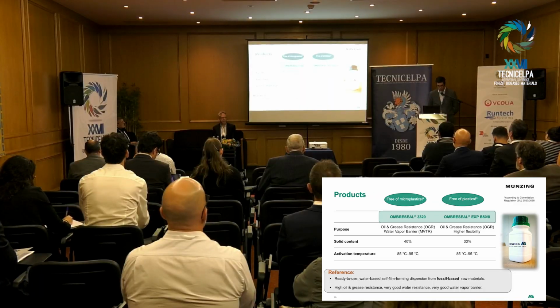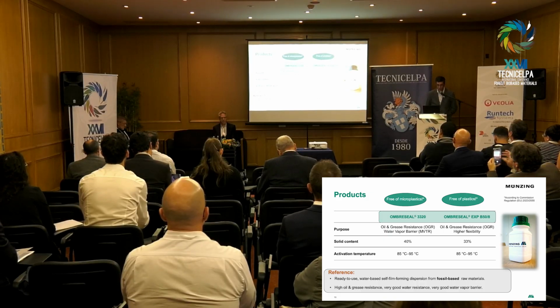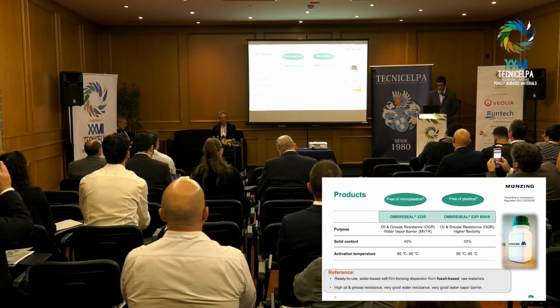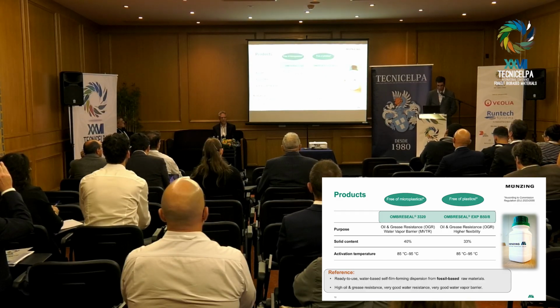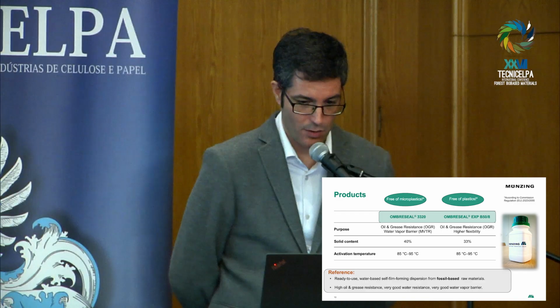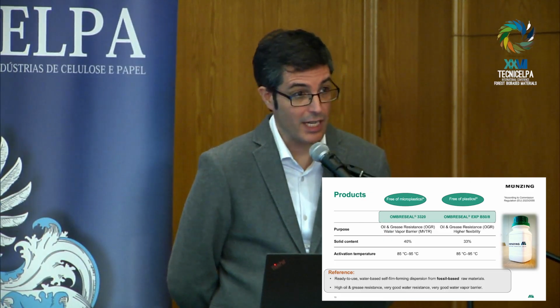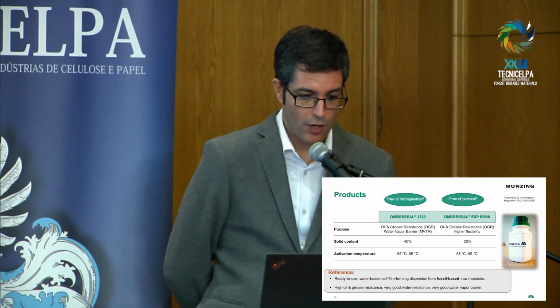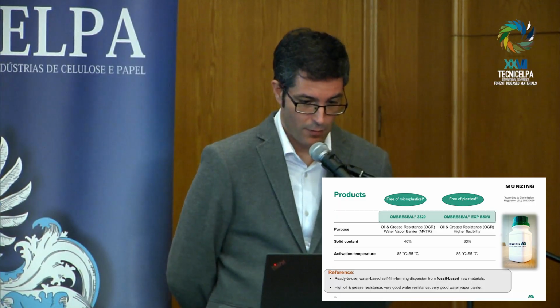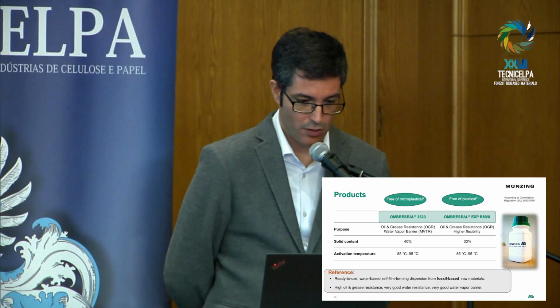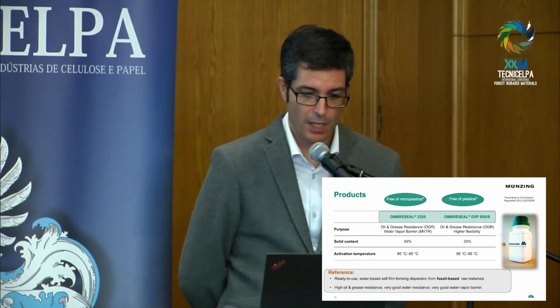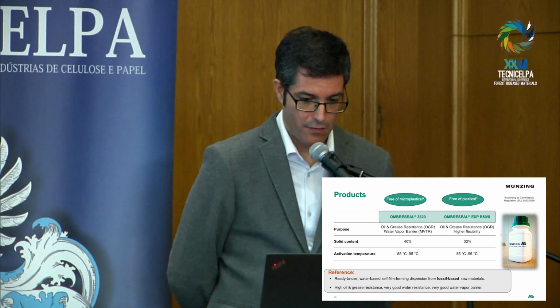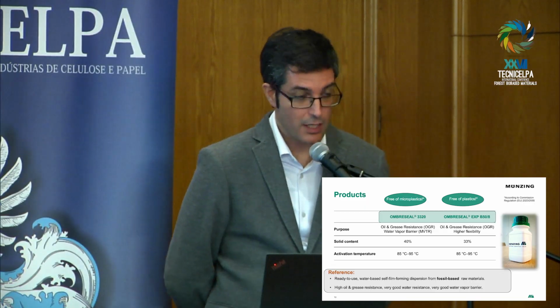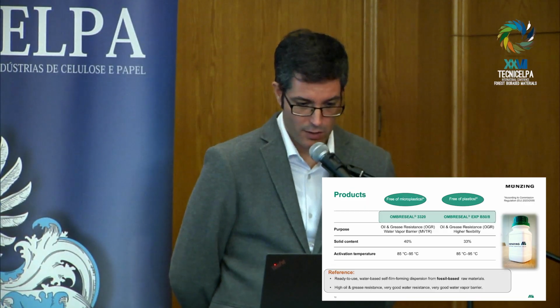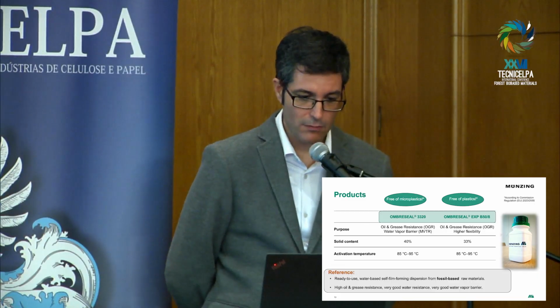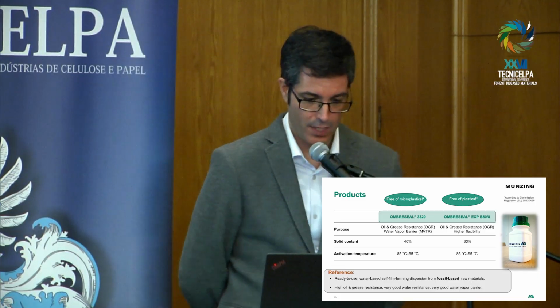The two products that I want to introduce today are the OmbreSeal 3320 and the OmbreSeal EXP B50/8. The first product, OmbreSeal 3320, is free of microplastics according to the EU 2023/2055. It's good for oil and grease resistance as well as water vapor barrier. 40% solid content and activation temperature around 90 degrees. The second product is the EXP B50/8. It's also good for oil and grease with higher improved flexibility. The solid content is slightly lower, 33%, and the similar activation temperature around 90.